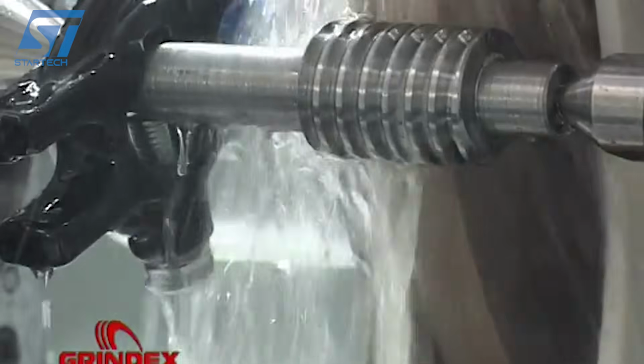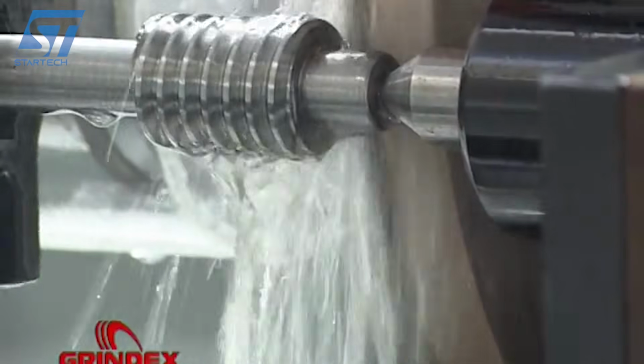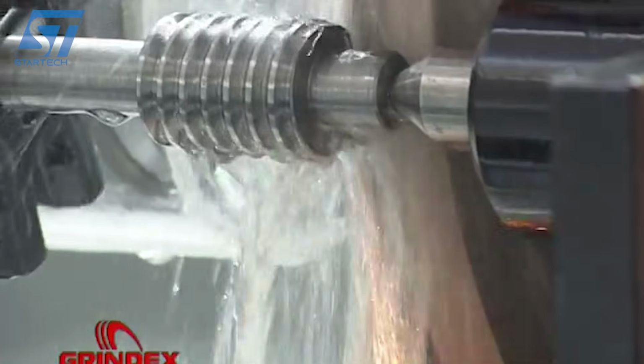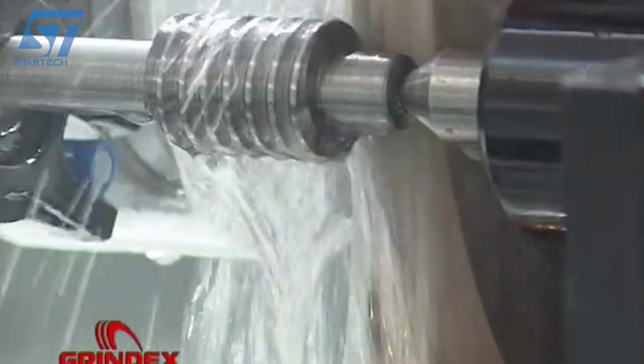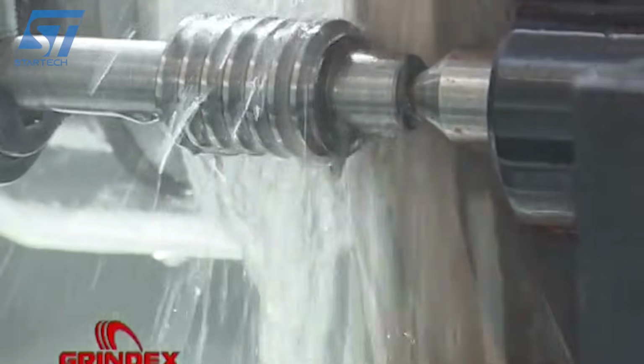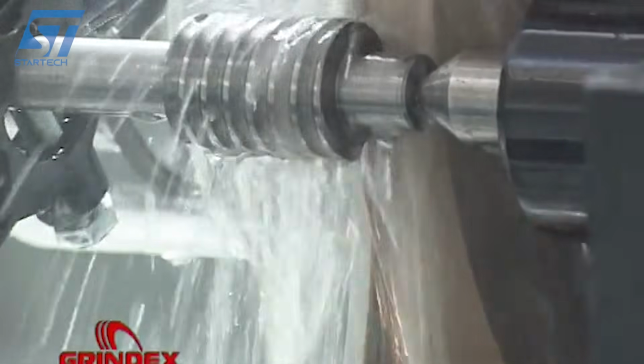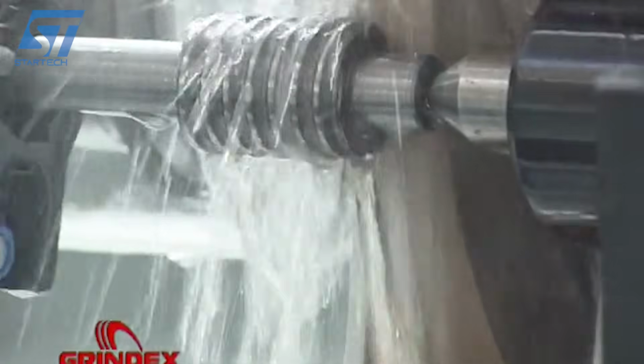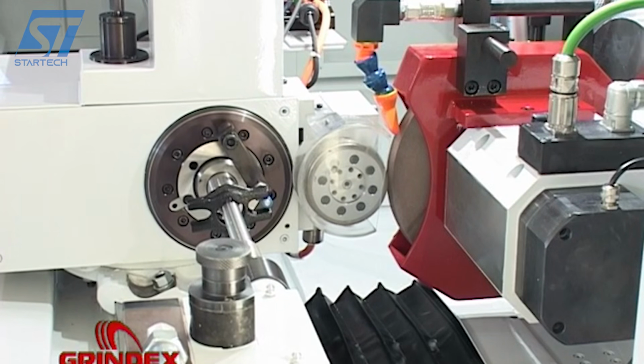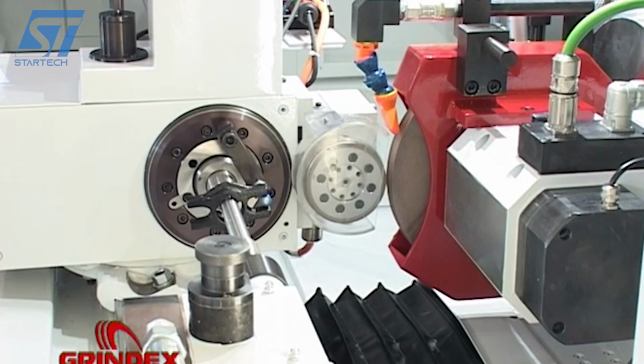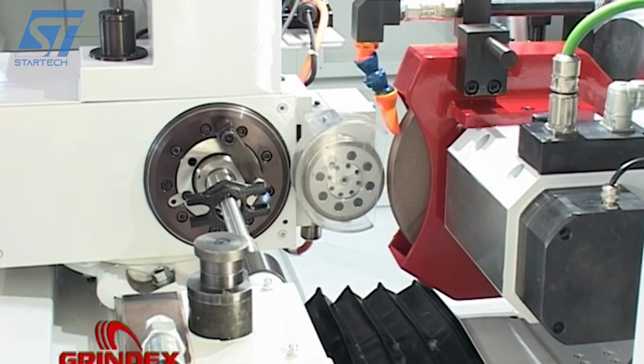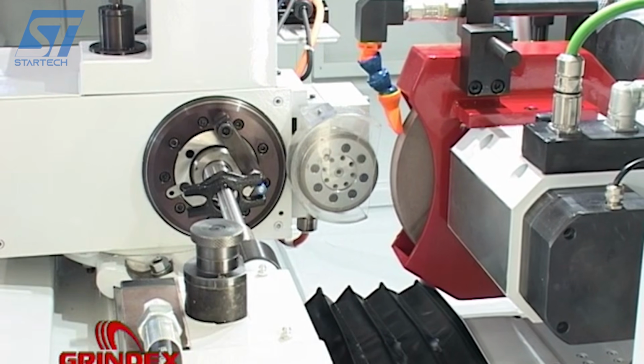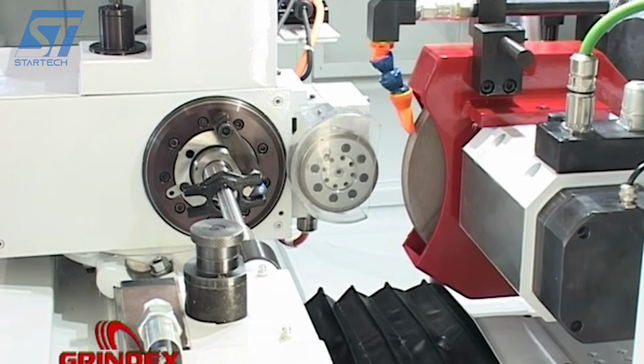The rotating workpiece advances along its axis while the spinning wheel contacts the thread flanks simultaneously. The precision of the resulting thread isn't measured in thousandths of an inch, it's measured in micrometers. The coolant system on this machine is also worth noting. High-pressure filtered coolant is delivered directly to the grinding zone to flush away swarf, prevent thermal damage to the workpiece, and extend wheel life.